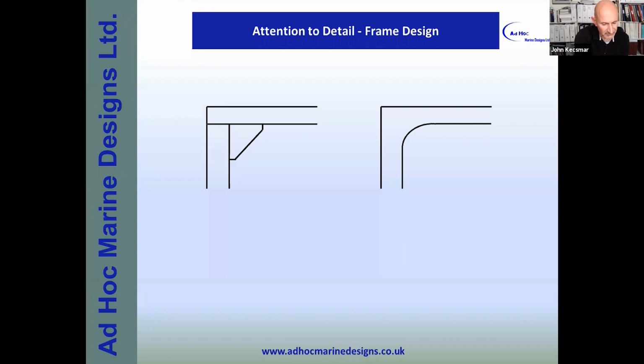We can create a generic idea of what frames are like. There's ostensibly the straight line method, and there's the more curvy method. If we take the straight line method, this is very good for production, because you can simply use extrusions and just weld them together at right angles or whatever angle they're at, and simply put in a nice bracket. Whereas on the right, this is nice and curvy, it looks good, but it does actually require a little bit more effort, because you have to produce the actual cut part, and that takes a bit more time. And then once you've done the cut part, you then have to bend and roll the rider bar, so there's a little bit more time involved. But each have their own merits.